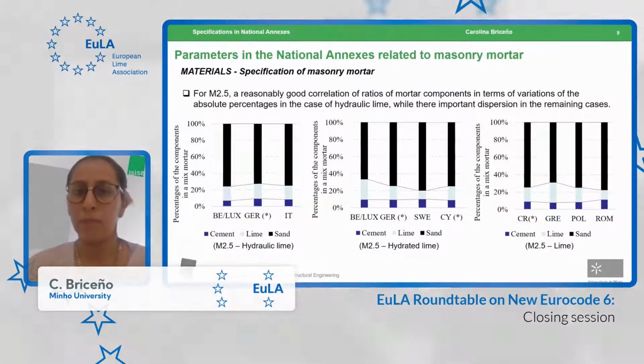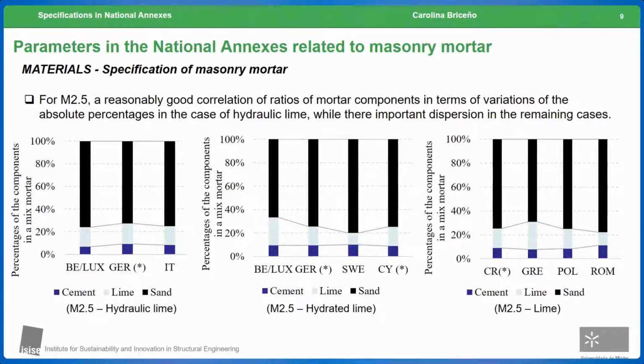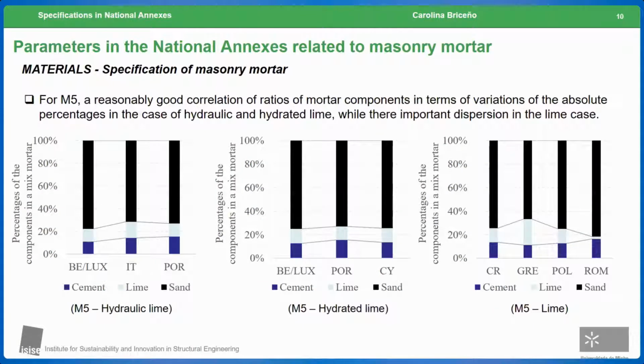Going into detail regarding the mortar mix proportion, here I show the comparison between the absolute percentage of the components in a mixed mortar for the mortar class 2.5, divided by hydraulic lime, hydrated lime, and also those proposals related to lime without any specification. We see that in the case of hydraulic lime, there is a good correlation between the ratios of the mortar components, which doesn't happen in the case of hydrated lime and also for lime without any specification. On the other hand, in the case of the mortar class 5, now this good correlation happens for the hydraulic and also for hydrated lime, but this doesn't happen in the case of the lime without any specification, and it is super clear in the case of the Greek proposal against the Romanian one.